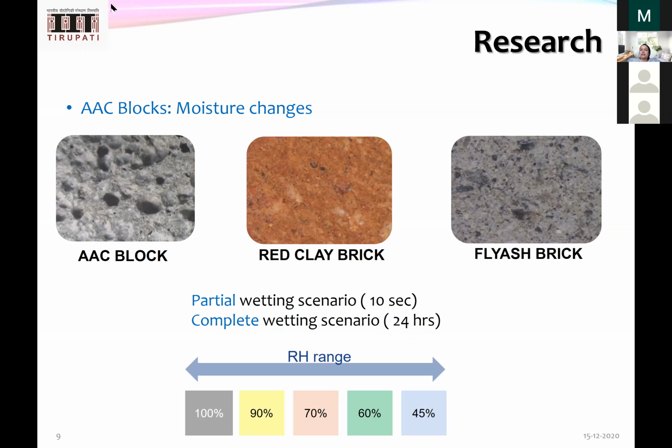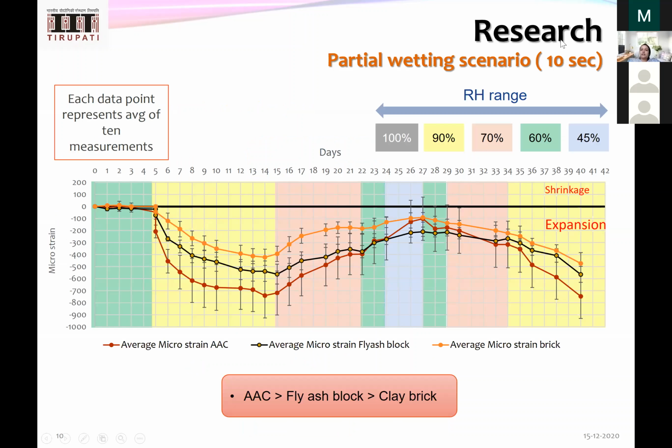To understand that, as I said, we first started with a partial wetting scenario where we have only 10 seconds of wetting. Then I varied the relative humidity. If you see this graph, I started with 100%, 60% relative humidity, then moved to 90% relative humidity. Here my brick is just partially wetted and kept in the humidity chamber or climate chamber. We have a chamber where we can control the temperature and the relative humidity. Here a constant temperature of around 25 degrees Celsius has been chosen, but the relative humidity was varied. So what we found is,